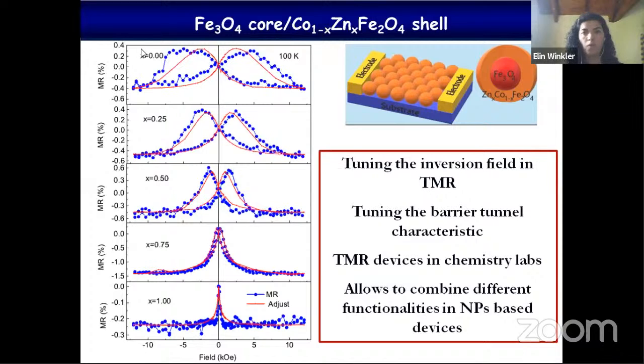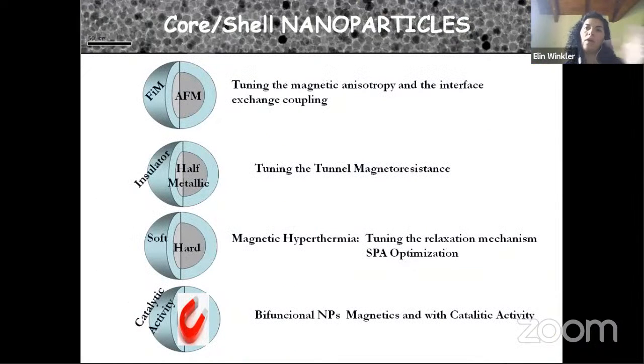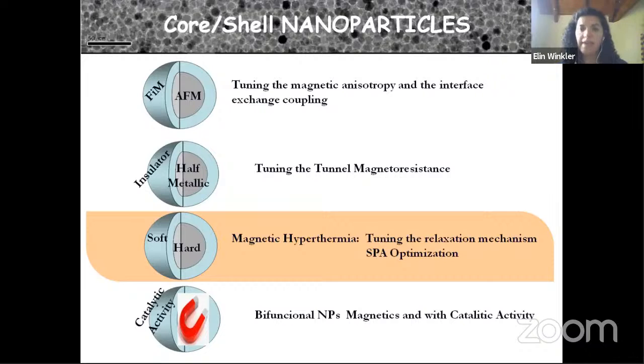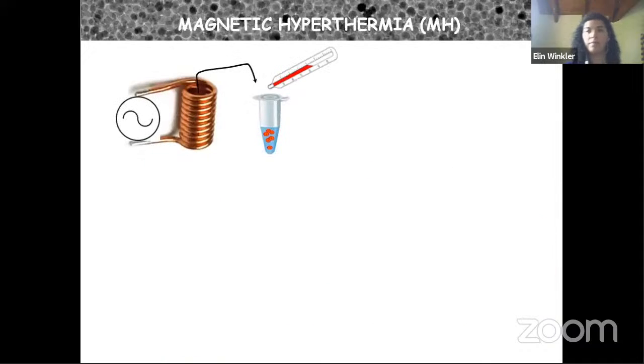One thing I have to say is that the value of the tunnel magnetoresistance is very low, but you can fabricate the system in a very easy way in a lab. So you can test many different materials. And also a very important thing is that you can combine different functionalities. Here we use a magnetic insulator, but you can use a ferroelectric or another material with different properties. So we can play with and design many different systems. We are going to use all these things that we learned here to improve the properties of the material for magnetic hyperthermia. So we are going to biomedical applications.